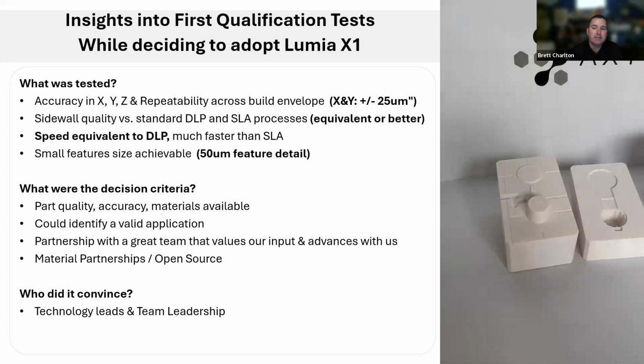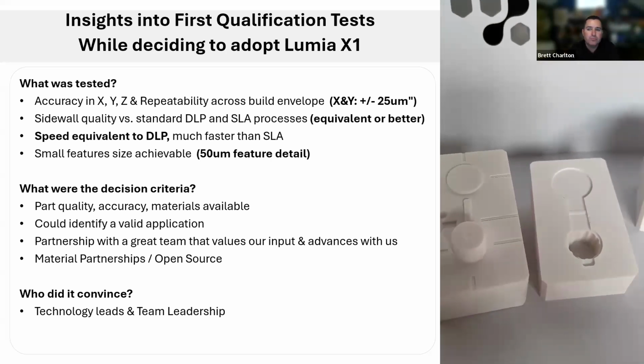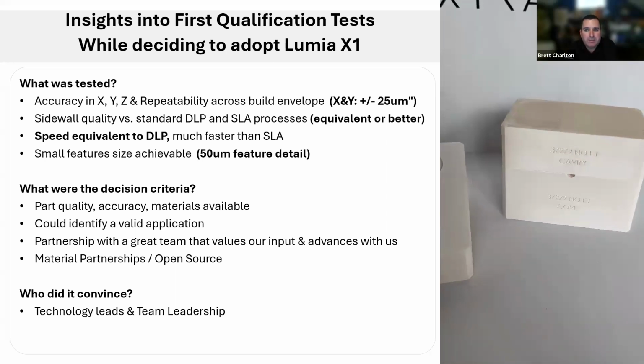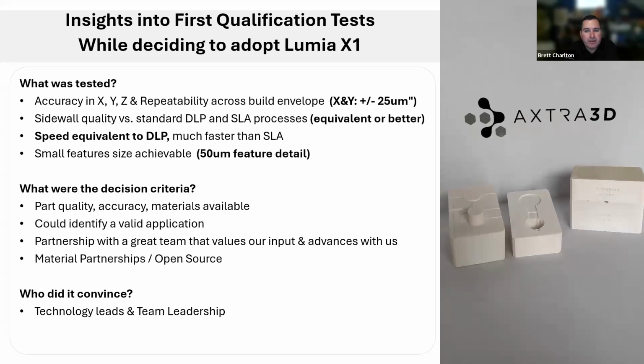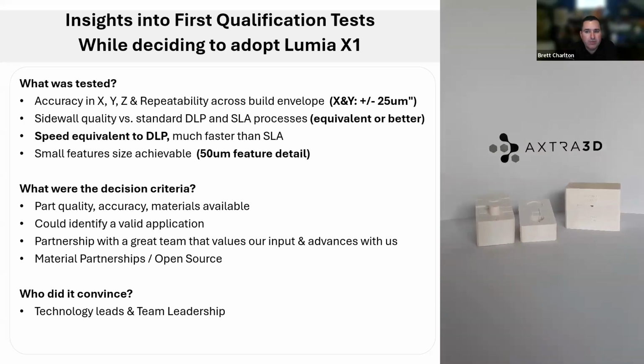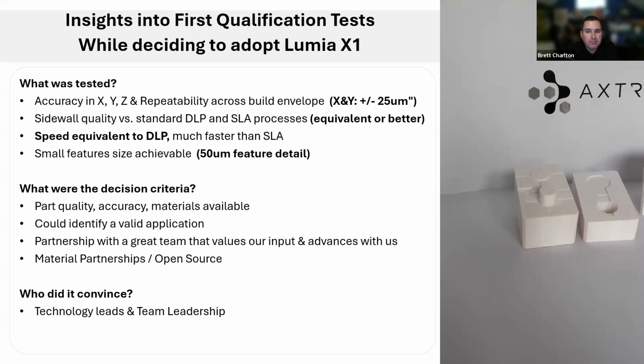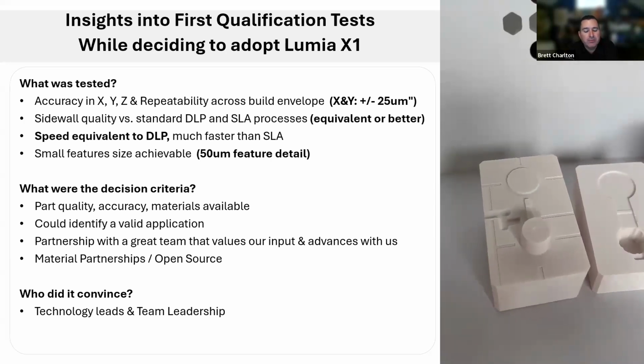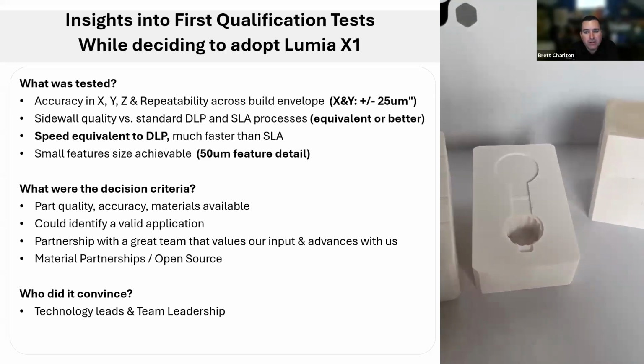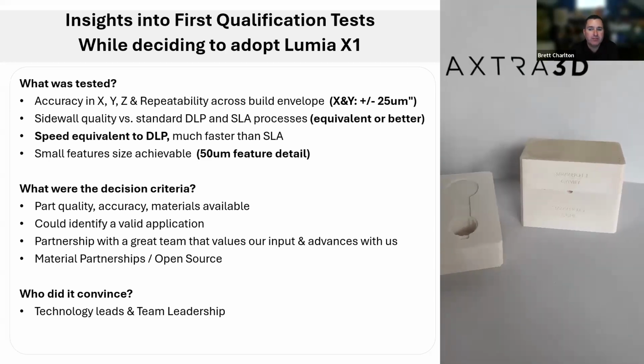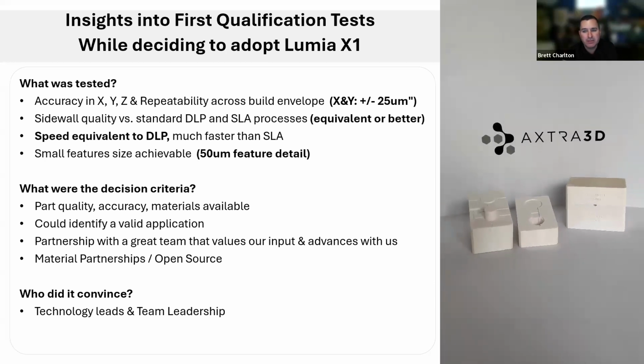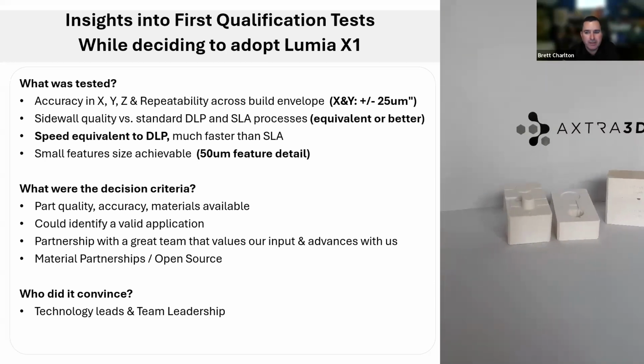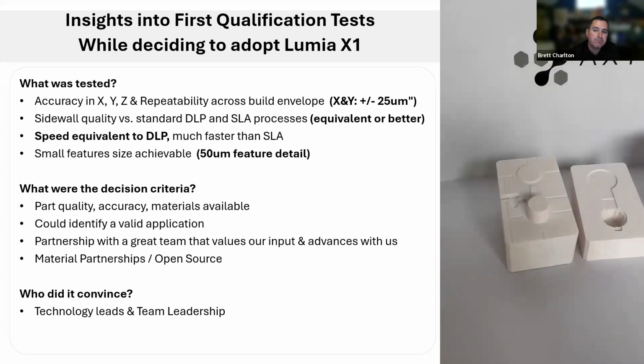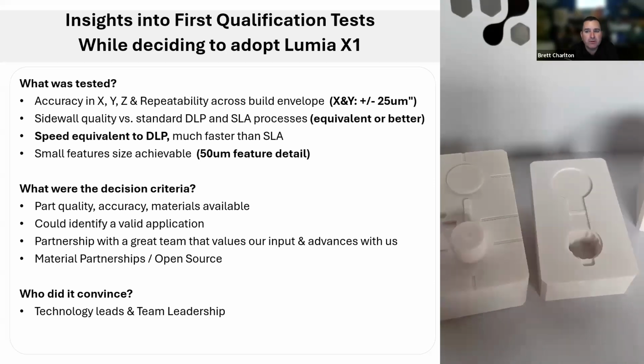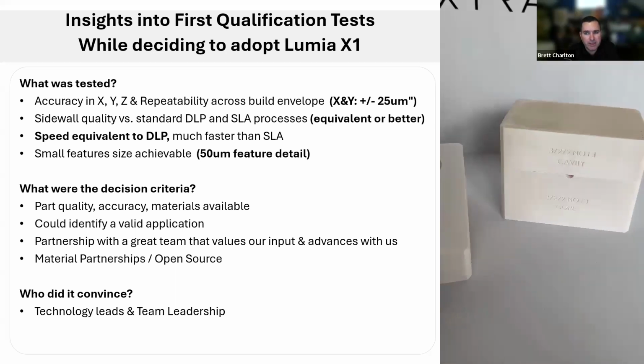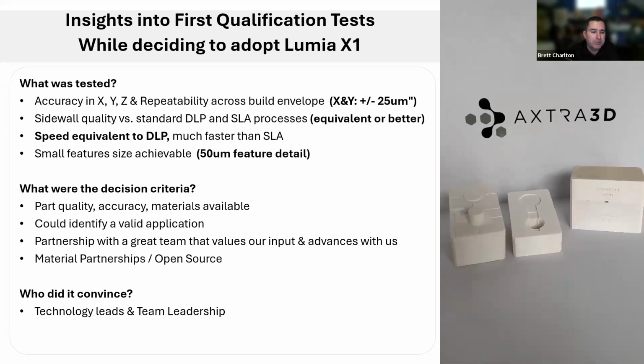Next, we compared SLA and DLP printed components versus those printed with Axtra HPS technology. Hands down, the HPS is faster than SLA, and it delivers a similar sidewall quality. When it came to comparing HPS versus DLP 3D printing, we were happy to see that the print speeds were similar. And while not all parts printed on Axtra showed a visible difference in the sidewall quality to the naked eye when compared to DLP technologies, they were always comparable, and in many cases, we did actually deem them superior. We also confirmed the system's capability to achieve the advertised 50 micron as a minimum feature size.